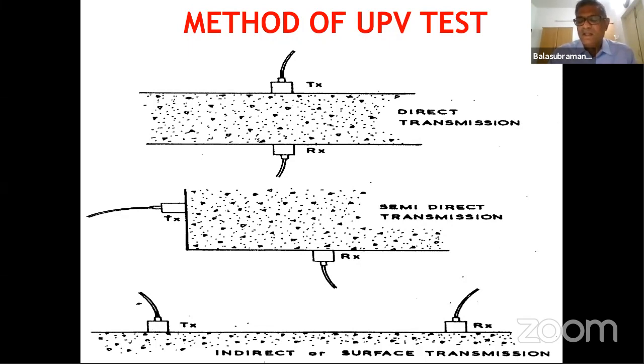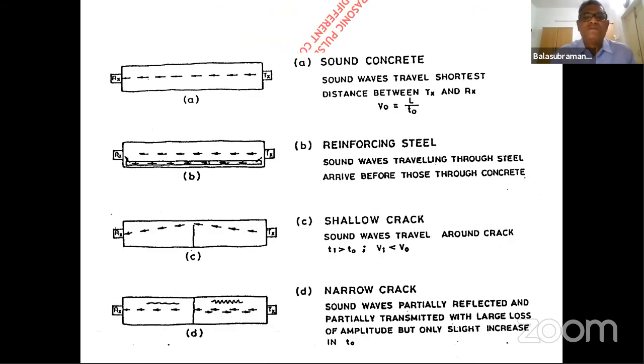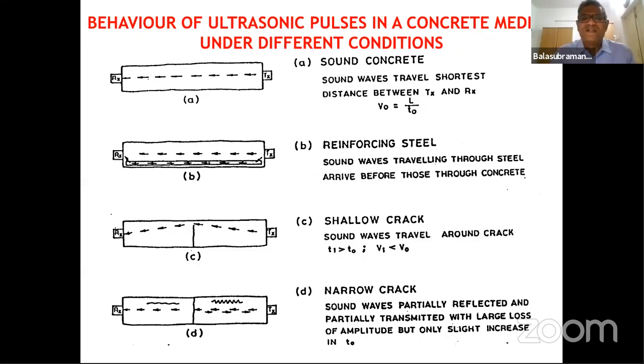Because sometimes I find that the width of the beam is about 30 centimeters. Sometimes when you apply the equation given in Bungey or in your IS code, you get a very erroneous result. So you have to be very careful while predicting the crack depth also. So this is something very common knowledge. If sound concrete is there, the waves will travel very fast. If there is some reinforcing steel, then it travels much faster. But then we don't apply a correction factor for the reinforcing steel because, as we'll see in the next 2 or 3 slides, the range of numbers given to predict the integrity of the concrete is so wide. So the reinforcing steel may not have such a great impact.